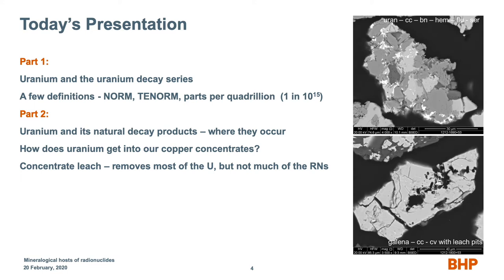This is a particle about the same size. It's chalcocite and covellite, and it has some bright spots in it. You see a lot of holes in it, and this is a particle that has gone through concentrate leach, so all those holes are actually uranium dissolving. And if it was very, very dark in here, we would be able to see little tiny specks of white all over that surface. And those little specks of white are uranium.